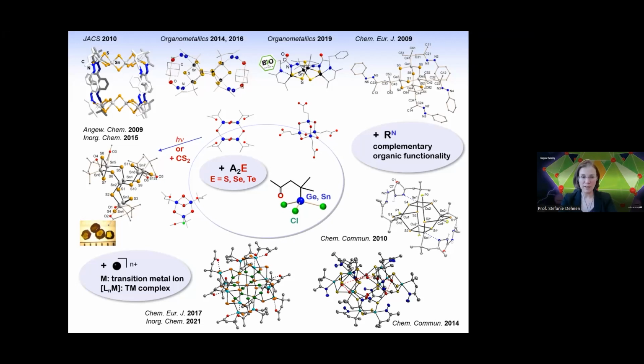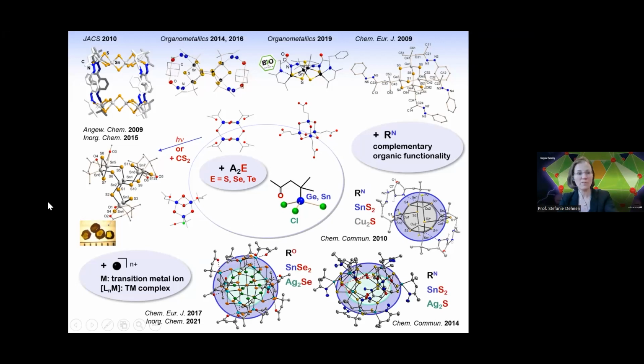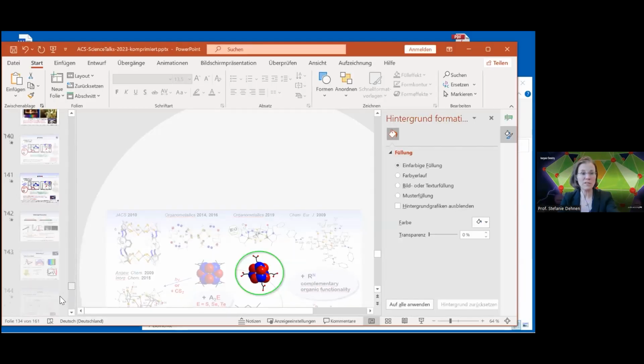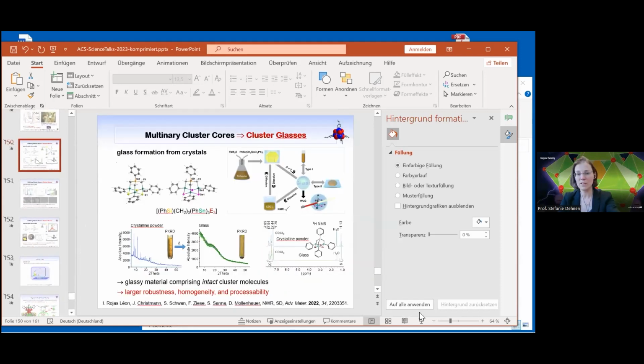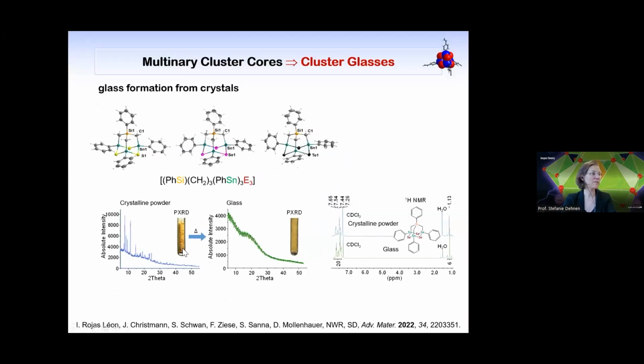In regards to the temperature as such, I can tell you that these clusters can be even molten without decomposition. And this is something I couldn't show you for the sake of time. But here you see that easily. What we can do, for example, with these white light emitting clusters is that we melt them, and you have single crystalline compounds in the beginning, you melt them, they get amorphous, but you can show by NMR spectroscopy that they are still the same. So you have temperatures of around 200 degrees C or 150 degrees C to melt them, and they easily stand it. And this is valid for these clusters, and this is also the case for the ionothermally approached clusters.